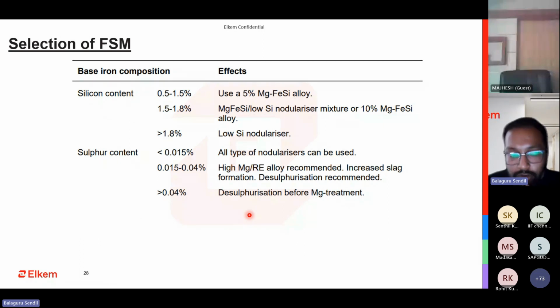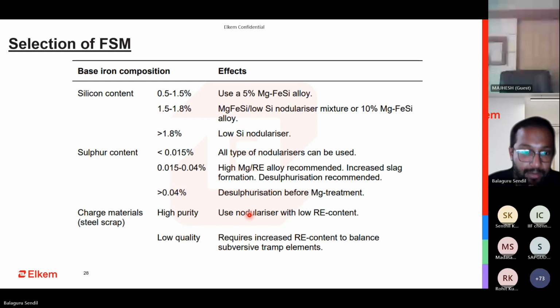If you're having more than 0.04, then you can try a pure magnesium treatment. Sometimes cored wire also can be tried here. Charge material: if you're using high purity scrap, use a nodularizer with low rare earth. Why? Because, as I told, rare earth is used for controlling the impact of subversive elements.